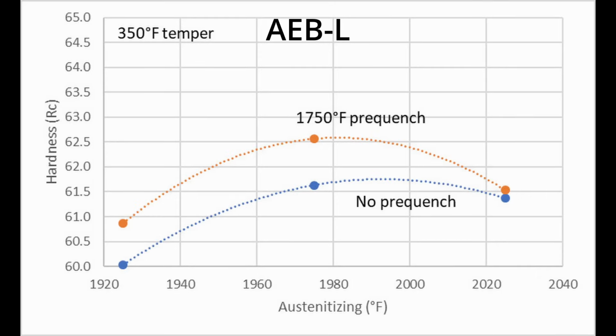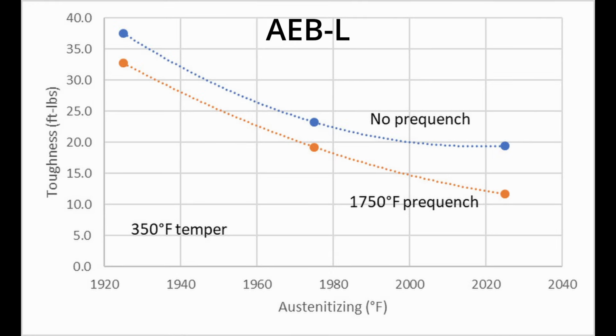Now, I have studied this with a couple different steels. One was AEBL. We tried prequenches of 1650, 1750, and 1850 Fahrenheit, and then followed that up with 1925 or 1975 as the final austenitize. Now, when the 1750 prequench was added, the hardness was higher and the toughness was lower. This is because during the initial austenitize, we dissolved some carbide, and so on the second go-around, we didn't have as much carbide to dissolve, so more carbon goes in solution, even though our final austenitizing temperature is the same. So this increases hardness and it reduces toughness.